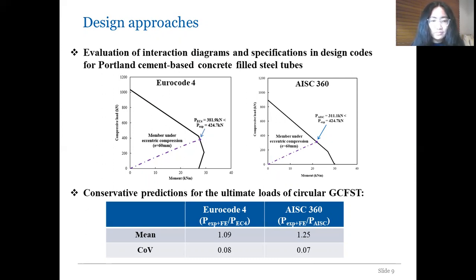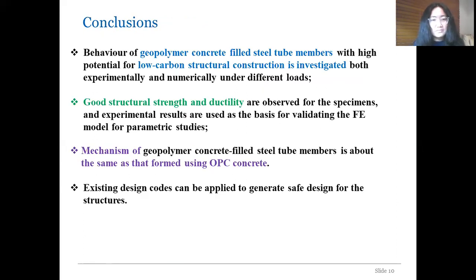So subsequently, I performed the statistical evaluation of the design codes using the experimental results I obtained, as well as the results from the parametric studies. The evaluation outcomes are shown in the table at the bottom. On average, the design approaches in these standards provide conservative strength predictions, so they can be safely applied to the design of the circular shape geopolymer concrete filled steel tube structures. Compared with the American standard, Eurocode is more accurate. So that's the main part of the presentation that I wish to talk about.